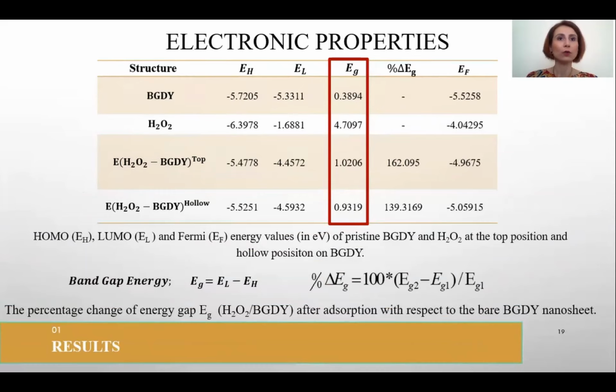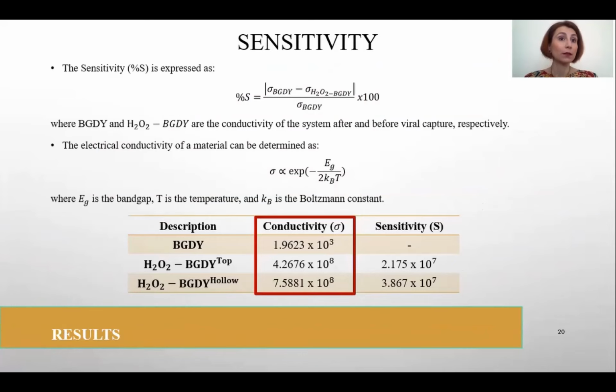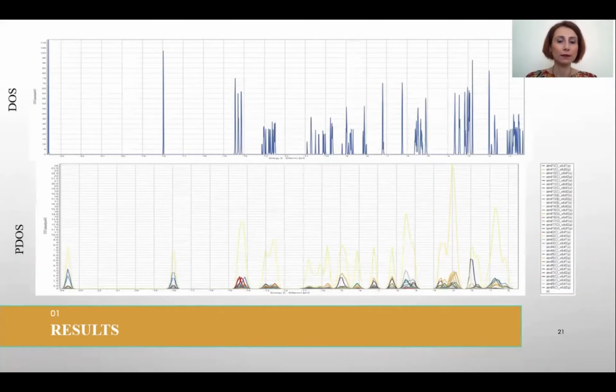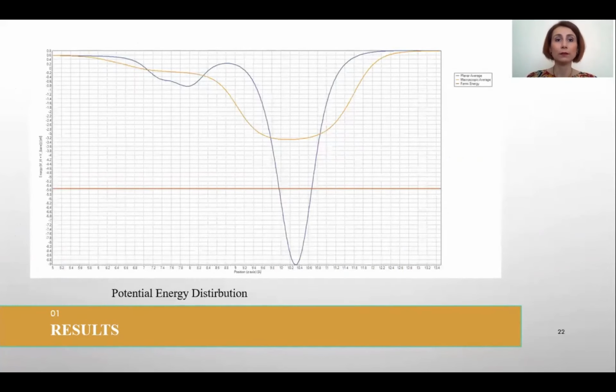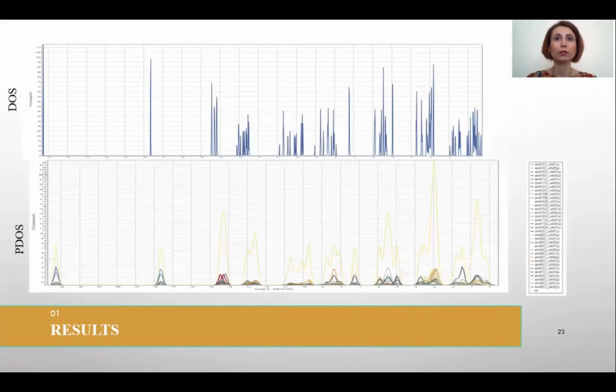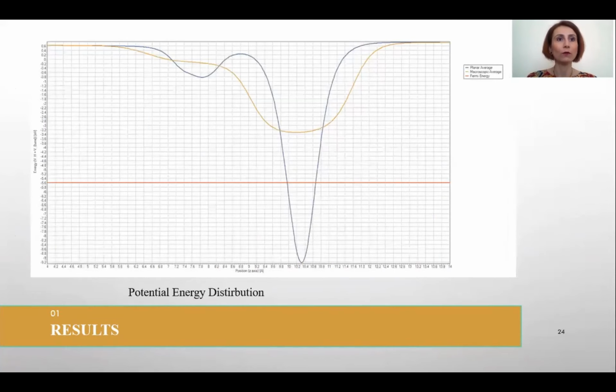By using the highest occupied and the lowest unoccupied levels, we computed the energy gap and the Fermi energy values. In both positions, the energy gap becomes larger. The conductivity is greatly changed after placing hydrogen peroxide on the boron graphdiyne. The adsorption of hydrogen peroxide has a significant effect on the conductivity. Density of states, projected density of states, and potential energy distribution are drawn for both positions.